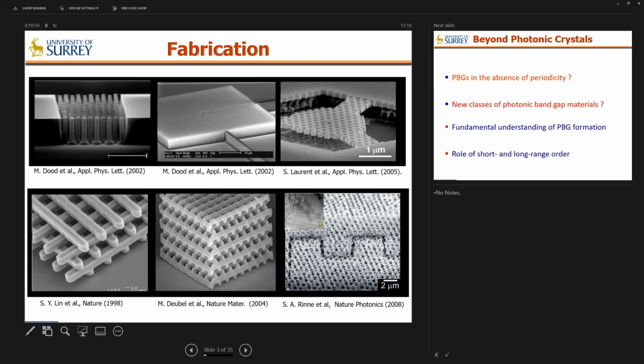And we have some other very interesting examples shown in this figure here on the right-hand side, in which we start with an opal structure. You see the structure here on top, which is precisely the structure that we see in the opal, an FCC arrangement of silica spheres in air. And what we do, we infiltrate this structure: in the air voids, we place a different dielectric material, and then we etch out the original template of the silica spheres.